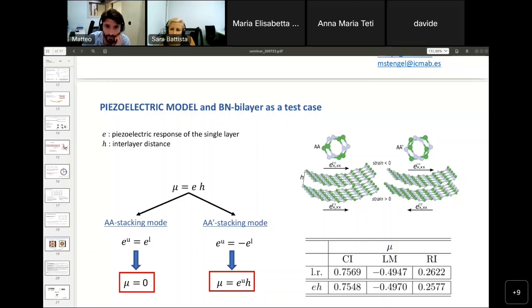Why did people overlook the metric term? Well, I'm not clearly sure about it, but I guess it's because people didn't see it. As I mentioned, people always tried to define flexoelectricity. If we speak about first principles, people always tried to look at the flexoelectric response in two-dimensional materials by use of the polarization. And indeed in the literature we can find a lot of disagreement about the reported values. This is also because of the definition of the thickness of the material that I mentioned before. So I think people overlooked the metric term because they always considered just the polarization, which, in principle, like every object defined in a curvilinear frame, brings with it a geometrical term.